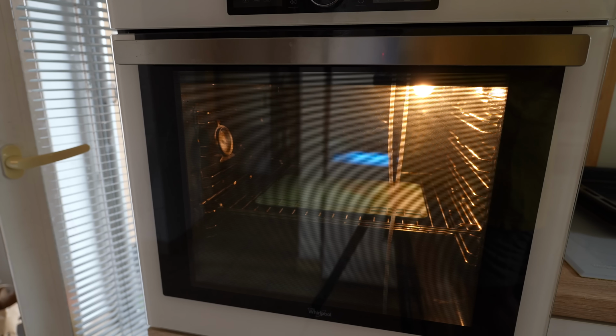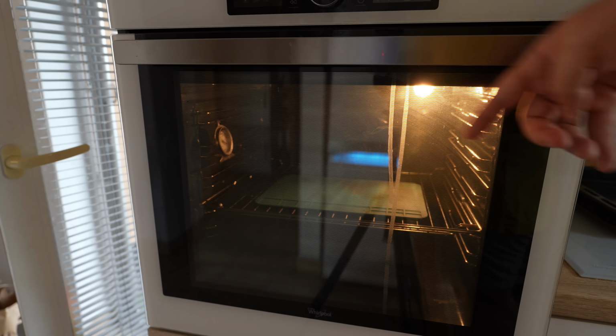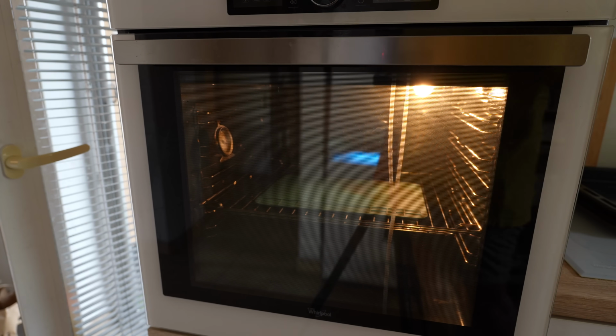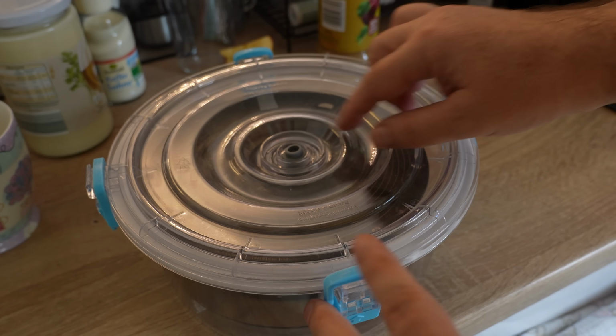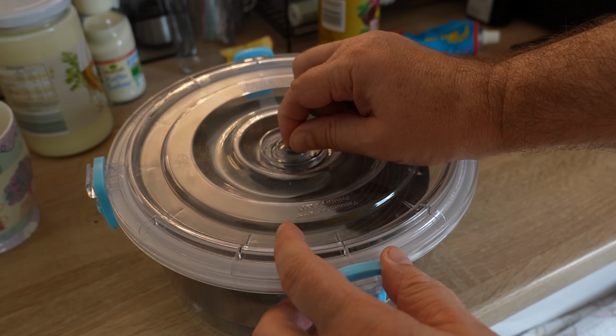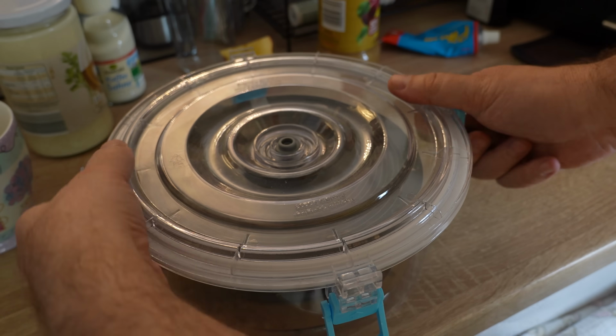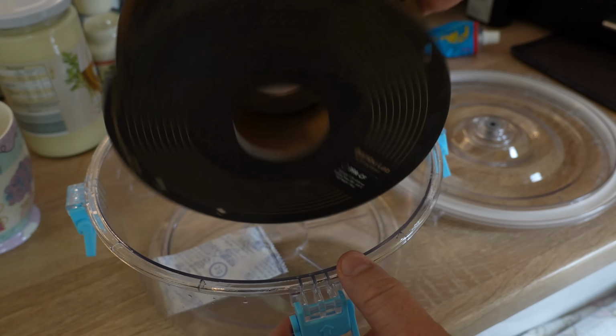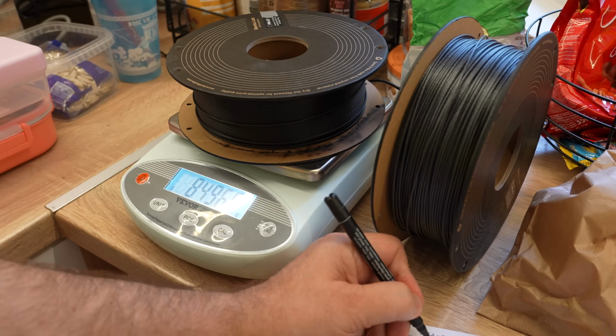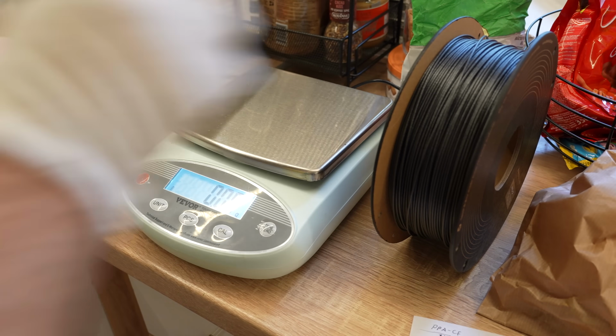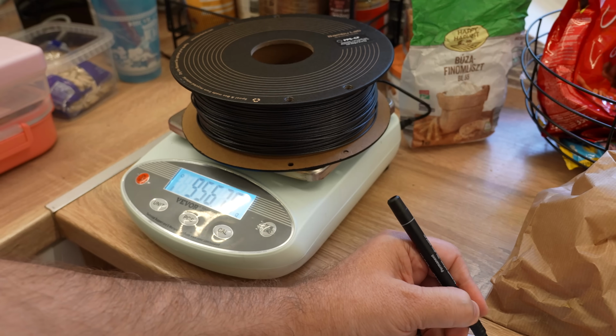The oven is preheated to 120 degrees Celsius, and I'm controlling the temperature with additional thermometer. And it will be dry together with the PPA-CF because I need some test objects from this filament too. If I will measure their weight every half hours, in that case I can calculate how much moisture they had in them.